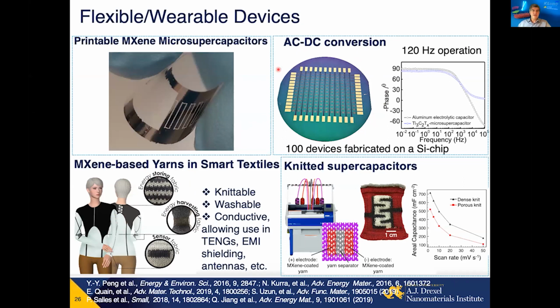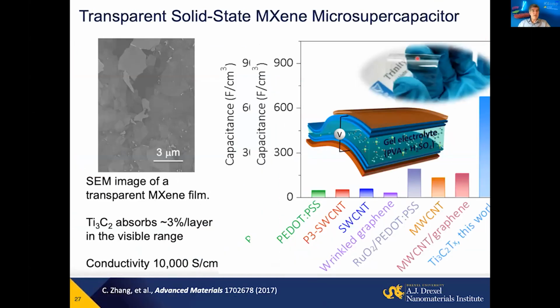Here are 100 printed supercapacitors on a silicon chip, showing actually close to 90-degree phase angle and high frequency behavior, making them useful potentially for AC-DC conversion, competing with aluminum electrolytic capacitors with orders of magnitude smaller volume. And we also work with Professor Hoseok Park from SKKU to show similar or even actually faster performance for MXene conducting polymer nanoscale devices. And it's possible to make transparent supercapacitors.